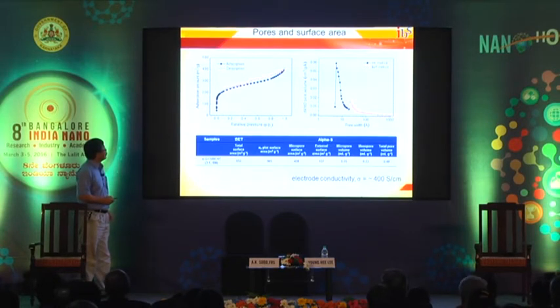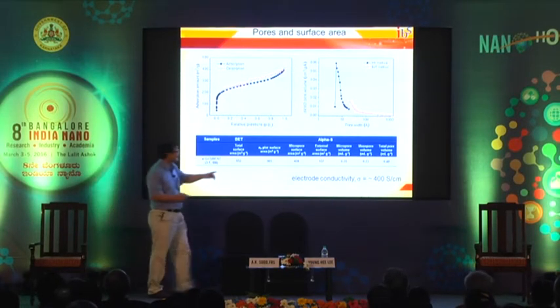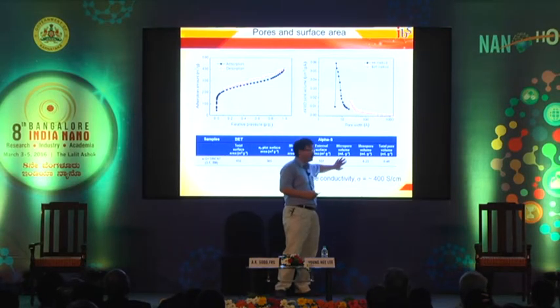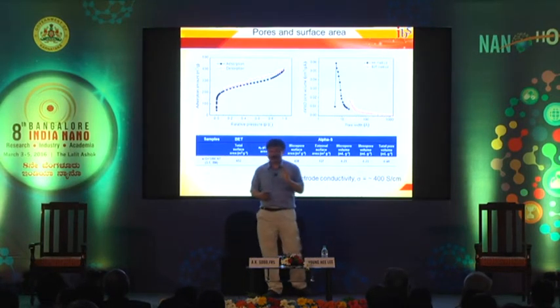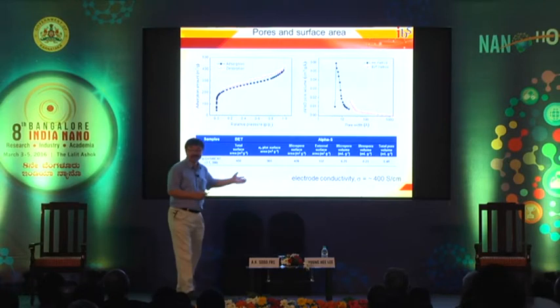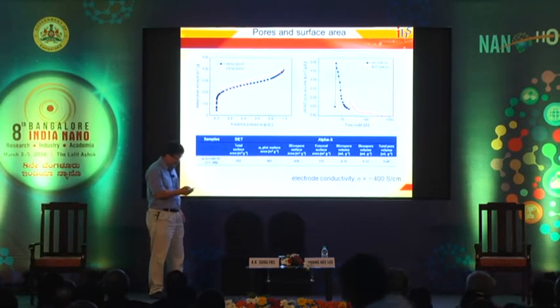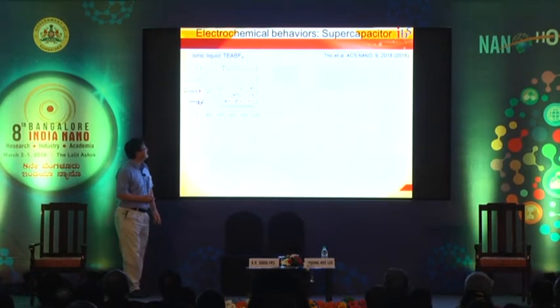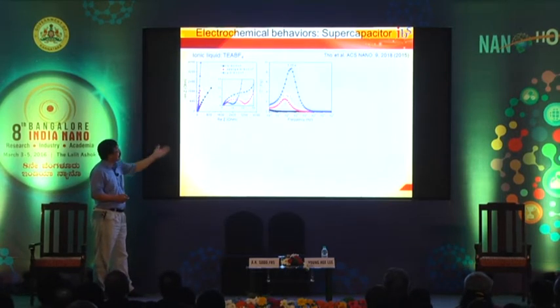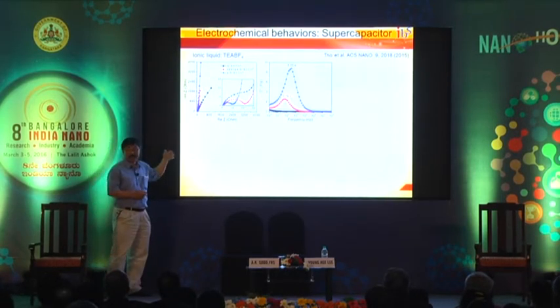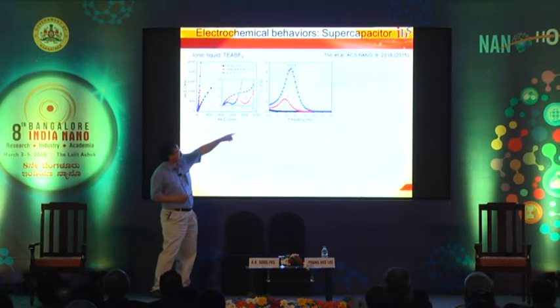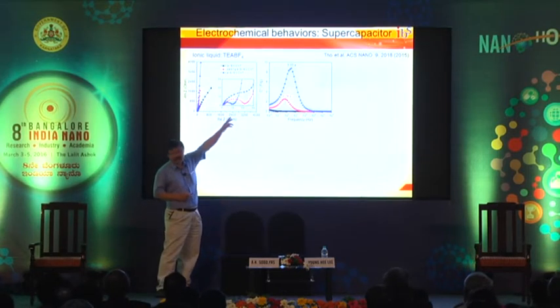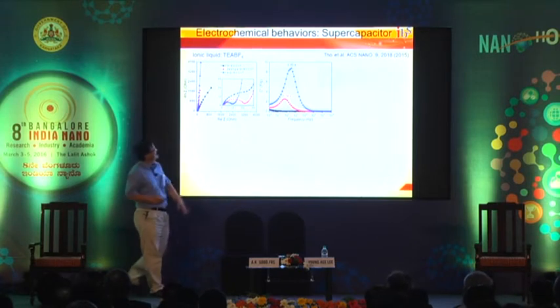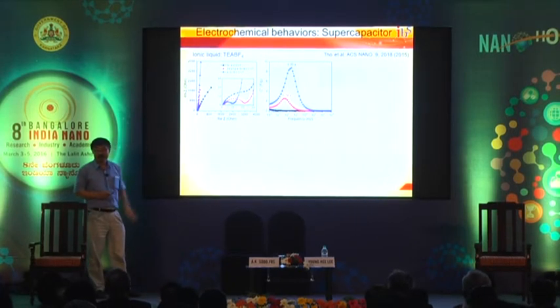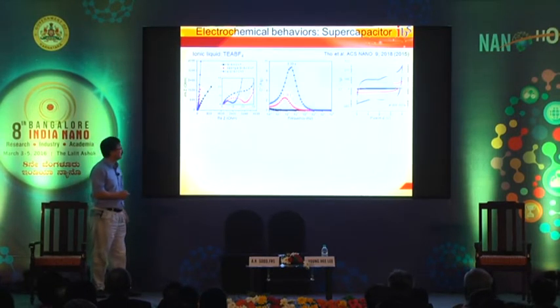Since I don't have time, one thing I like to emphasize: we have a certain amount of micropores and a certain amount of major pores. This is very important. We optimize this structure, and conductivity is also still very high. Ion relaxation or ion diffusion can be represented by this value. Our sample actually has a very low value, which means ion diffusion is fast.